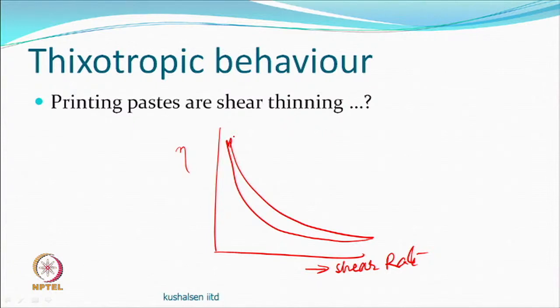Regarding using polyelectrolyte synthetic thickeners for all types of printing: theoretically yes, as long as there is no pH change. If any anion–cation combination occurs due to additives, viscosity will suddenly fall. As long as you keep the system neutral and ionic concentrations stable, you may be able to print anything. This ionic and pH sensitivity is a characteristic specific to polyelectrolyte thickeners.